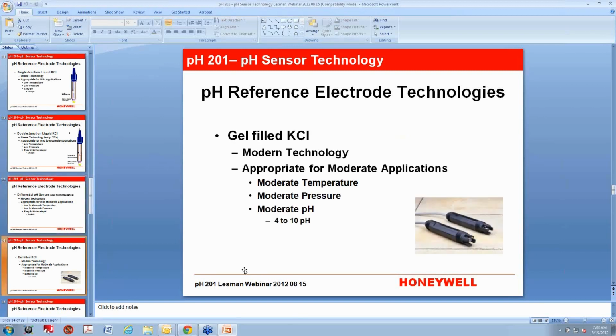Again, there's exceptions on those numbers always. Okay, the next one up is the gel-filled potassium chloride reference, and that is probably what I see out there more than anything else out in processes. It was a huge step forward. Between the liquid fill and the gel fill, the industry went through what's called a slurry-filled reference electrode fill. And that slurry was an attempt to make the fluid thicker so that process fluid couldn't get in, less compressible, harder to mix, etc.